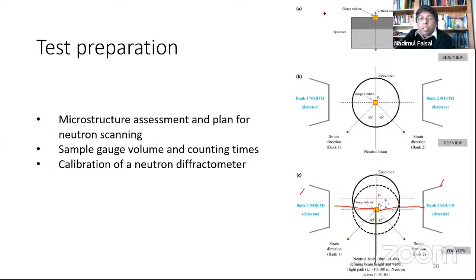If you see the cross-section view here, what we are doing is measuring from top to bottom, or you can go from bottom to top. So you do point by point. You can do a number of points in the coating and a number of points in the substrate. So there are two banks, which means you will have data coming from both detectors.